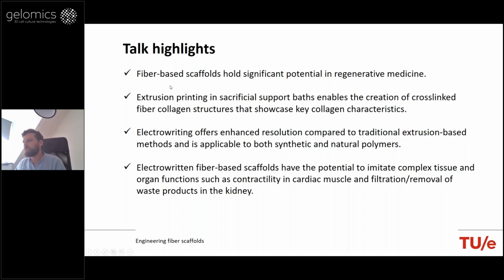So, starting again from the beginning, I showed that fiber-based scaffolds hold significant potential for regenerative medicine, and that extrusion printing in sacrificial support baths enables the creation of crosslinked fiber collagen structures that show some collagen hallmarks, in this case the banding pattern and fibril organization. I also showed you that electrowriting offers an improvement in resolution compared with traditional extrusion-based methods, and it is applicable to both synthetic and natural polymers. I showed you that electrowritten fiber-based scaffolds have the potential to imitate, and here it's really imitate, not resemble, some complex tissue and organ functions.